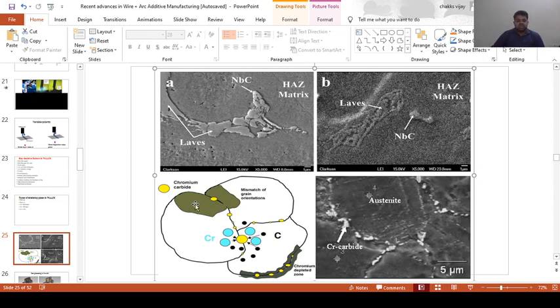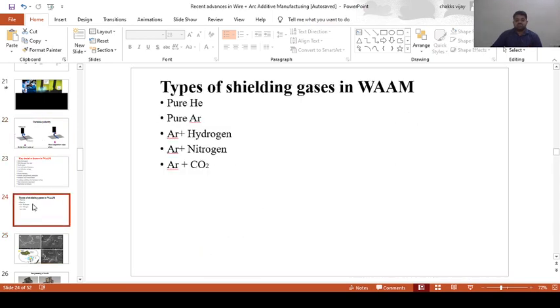If we want to avoid this chromium carbide formation, then we have to use certain shielding gases like argon nitrogen. Whenever we use argon nitrogen, the nitrogen will react with the carbon, because the reaction temperature is very high, and form nitrocarbides. Once the nitrocarbides are formed, there won't be any free carbon left to form chromium carbide. So when the chromium remains high in your stainless steel, it will be more corrosion resistant, and you won't face this sensitization issue. So the shielding gas is one of the most important considerations.